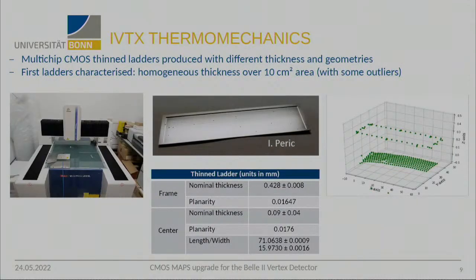Some first impressions: this is the first design of the thinned down sensor. On the edge we have sensors around 420 micrometer thick silicon, and in the center it's already thinned down quite a lot, in this case to 90 micrometer. We want to place 4 chips on it, and the first wafers are characterized, showing homogeneous thickness over an area of 10 square centimeters with some outliers, but this is very promising for the future.